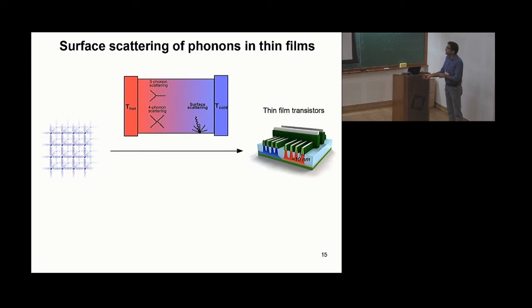One of the problems I wanted to look at is what happens to thermal conductivity as the thickness of the material is decreased. Fourier's law or any other equation I showed represents the thermal conductivity of an infinitely large sample, where only intrinsic scattering such as 3-phonon and 4-phonon scattering causes resistance to heat flow. But in a real device such as thin film transistors, you are thinning down the material, which means apart from intrinsic scattering, there is also scattering at the boundary or surface.